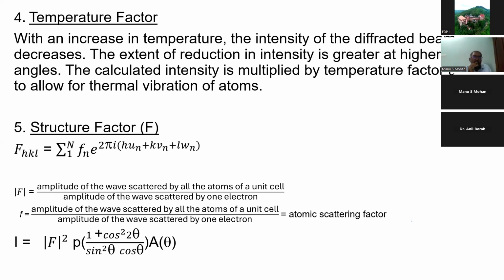Then you have the temperature factor. So what is temperature factor? As you increase the temperature, the periodicity is slowly getting degraded. Whenever you say X-ray pattern, you talk about the X-ray pattern at room temperature. At room temperature you have a periodicity, but when you heat it, the periodicity is affected, because the lattice atoms vibrate about its mean position. So that will affect the intensity.